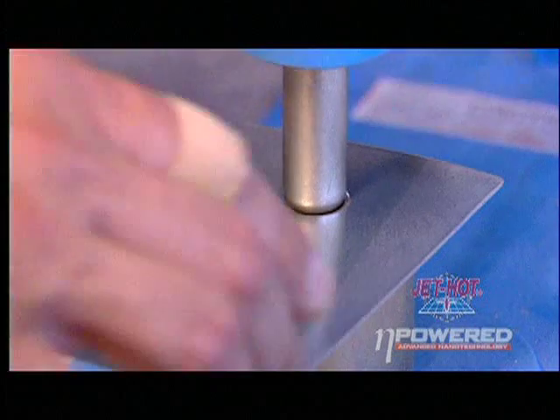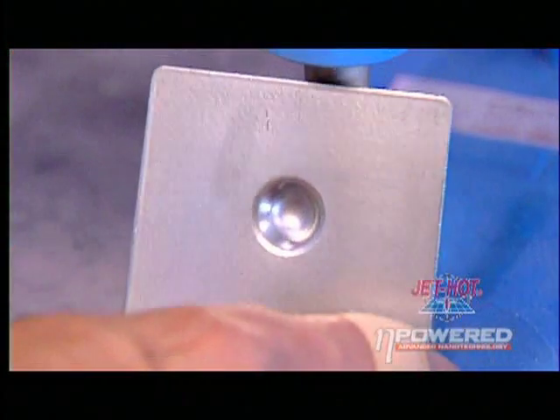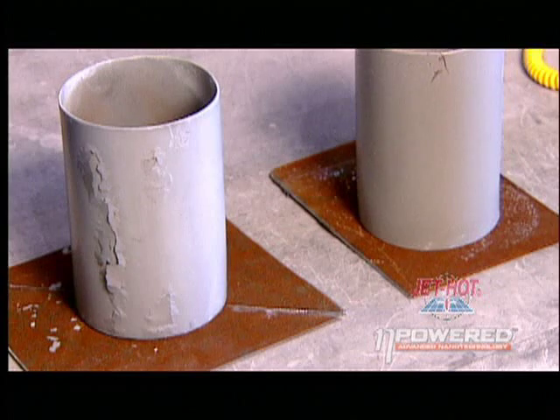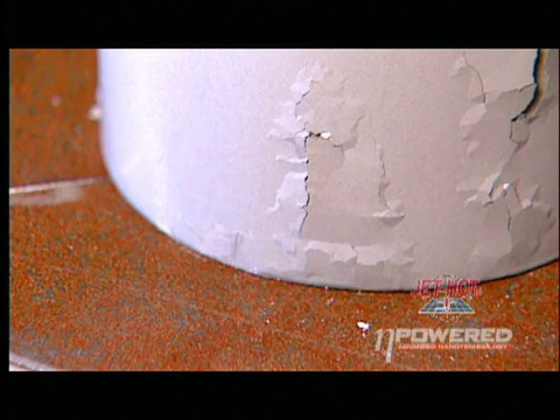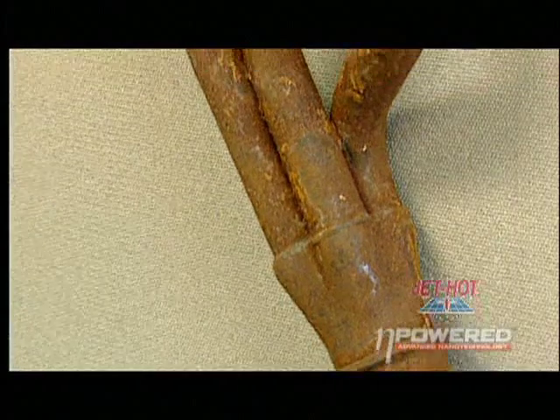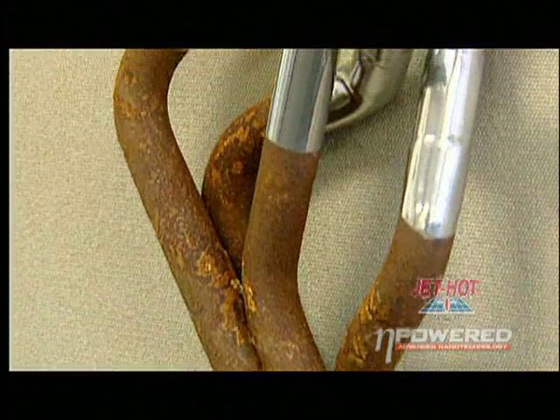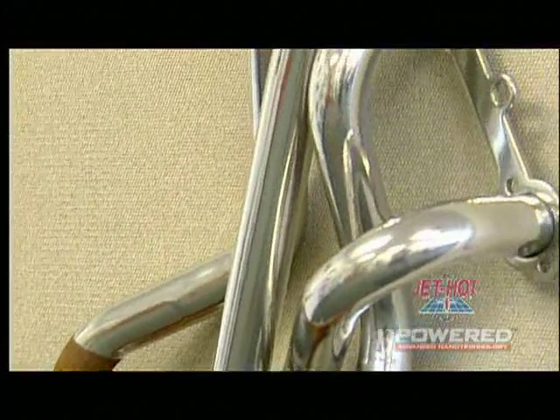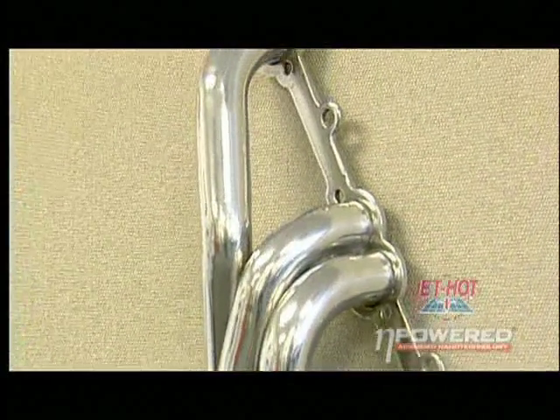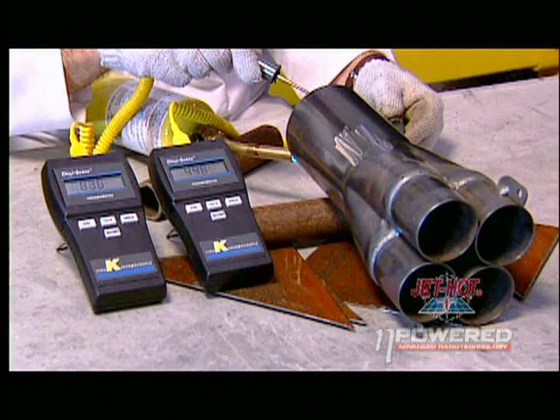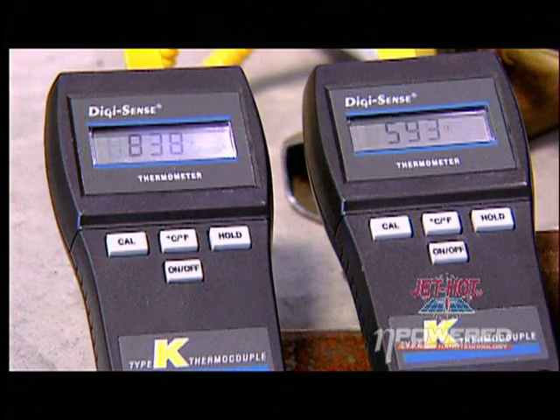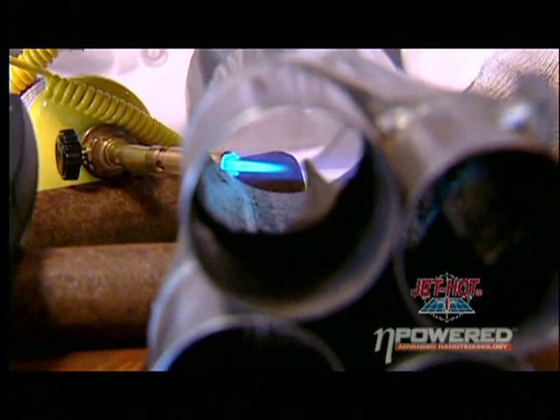Laboratory tests back up the field results. Using SAE and ASTM testing, we engineer the coatings to survive more punishment than any sledgehammer can put out. Here we see a conventional coating healing after being exposed to 1350 degrees Fahrenheit, while Jet Hot is still rocking at 1800 degrees Fahrenheit. And corrosion? Forget about it. Most coatings can only withstand 1,000 hours in the salt spray test, where Jet Hot went 5,000 hours without a failure. We also typically see a 300 to 400 degree drop in skin temperature of the pipe, depending on the coating used.